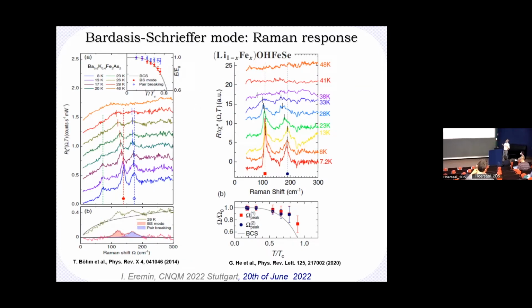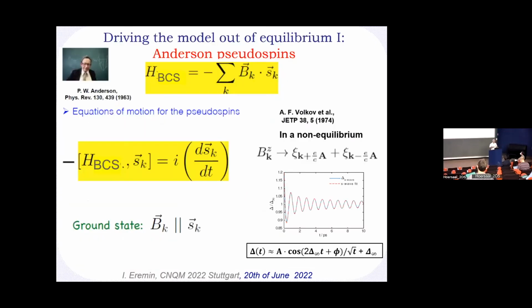So in various iron-based superconductors, such a B1g type of response in the S wave ground state has been observed. And what is also interesting is that there is a number of these modes that you see, and this is for an obvious reason, because the symmetry of the vertex is chosen such that it's picking up a B1g type of excitation. You see that there is a subdominant mode which appears in the linear response. Now, the natural first question to ask is whether in third harmonic generation or in a pump-probe type of experiments, you can visualize this mode, and whether its intensity will be similar to the Higgs mode, or maybe of the same order as the Bogoliubov quasiparticle, which basically gives you confidence that you are able to see it.